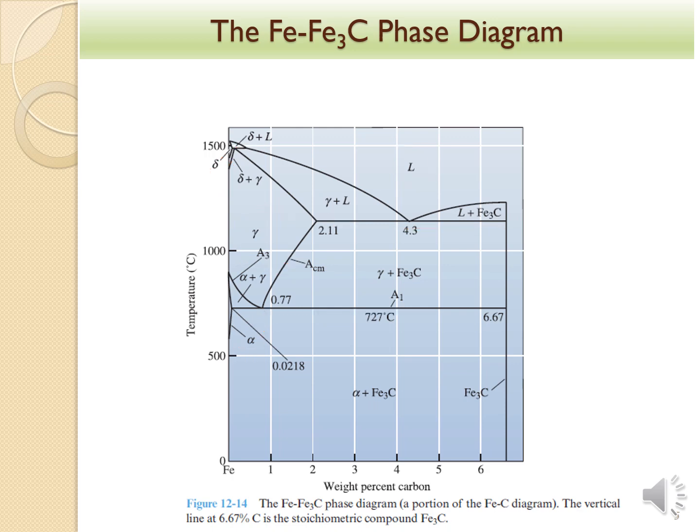Now let's see, where is the eutectic reaction? Eutectic is from one liquid to two solids. So this is the liquid, the gamma phase is a solid, and on the other side of the liquid we have this intermetallic compound, the iron carbide. So this is the eutectic reaction.